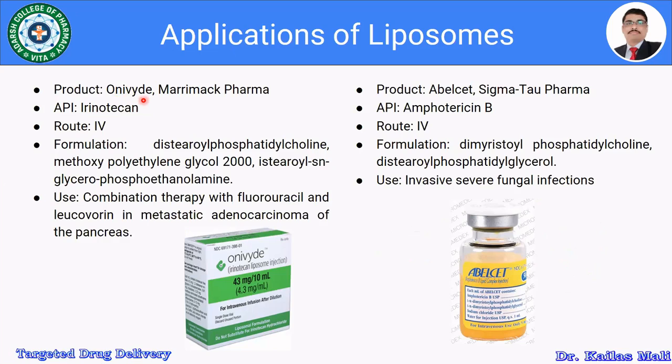Then Onivyde, it is yet another liposome based product which is developed by Merrimack Pharma, which contains the drug irinotecan. It is given by the intravenous route. The formulation comprises distearoyl phosphatidylcholine, methoxy polyethylene glycol 2000, stearoyl sn-glycerophosphoethanolamine. It is used in combination therapy with fluorouracil and leucovorin in metastatic adenocarcinoma of the pancreas. So this is a product, Onivyde.